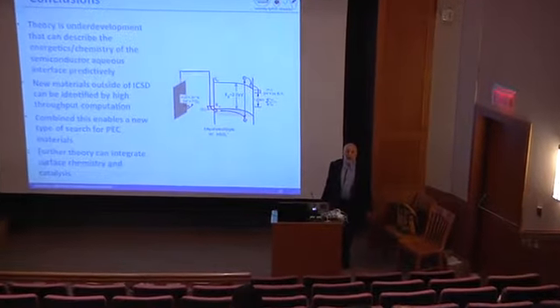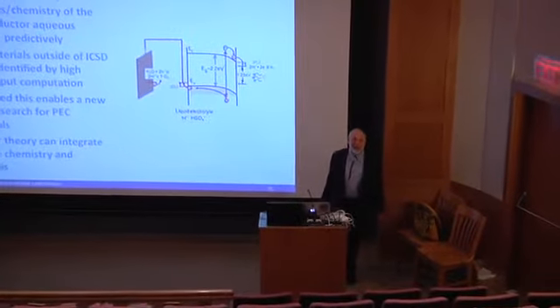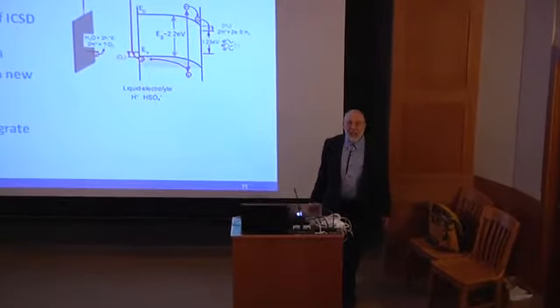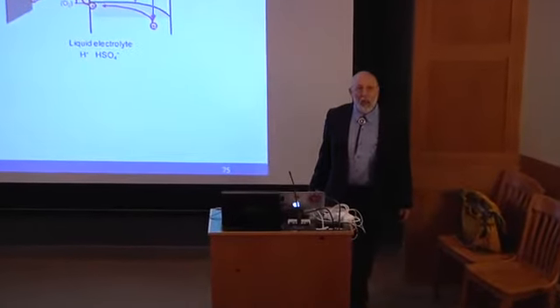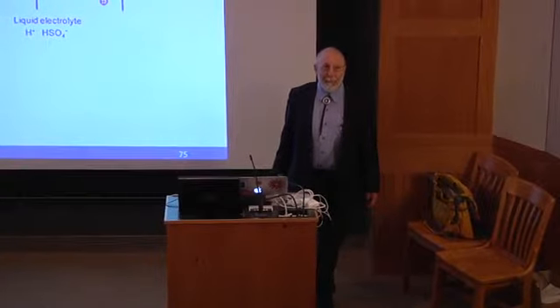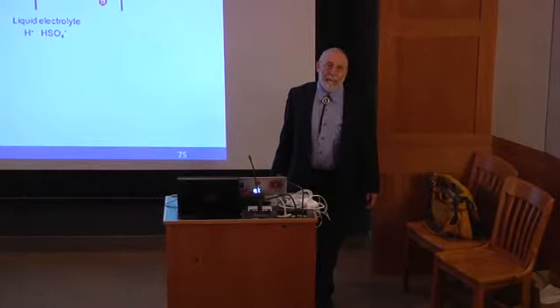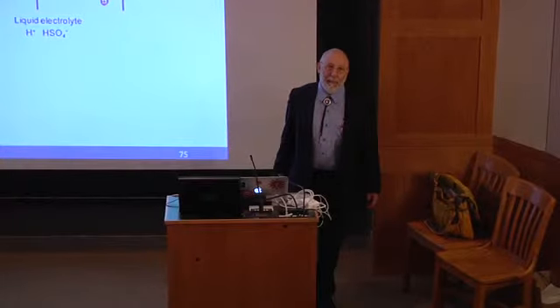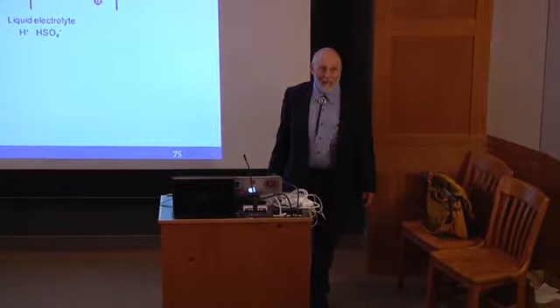I'm interested in this mysterious 0.5 electron volts. You show that this number is quite stable with different types of surfaces, even including oxides, selenides, and so on. But I'm wondering if you have differences in surface dipoles, for example, polar surfaces and non-polar surfaces, and those surface dipoles could introduce differences in water structures around that surface. Would that actually change this number, and by how much?